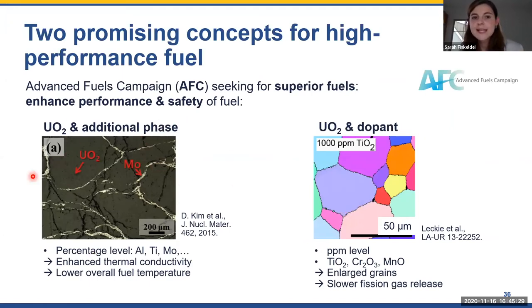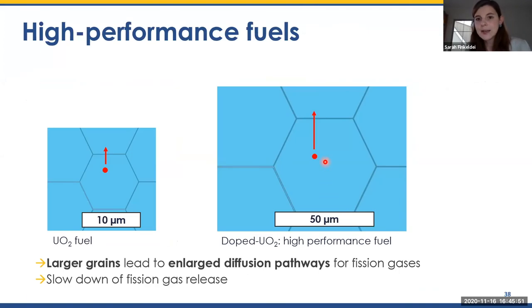So the concept here is that one concept of enhancing the properties of the fuel is to add a second phase so that you could increase the thermal conductivity of the fuel. And this one is a different concept where we are trying to make the fuel safer by enlarging the grains as the ADOPT fuel does from Westinghouse, so that we elongate the diffusion pathway of fission gases to the grain boundaries, and therefore hopefully slow down the diffusion of fission gases overall, so that they are not escaping the fuel and accessing the pellet fuel cladding gap, which could potentially cause a high buildup of the fission gases in the cladding, and could cause, in the worst case scenario, a burst of our cladding material.